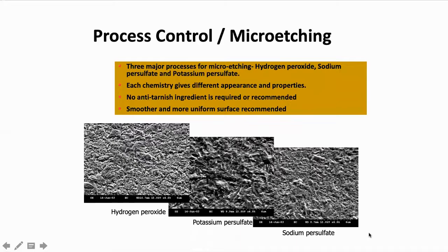So again, process control. I can't stress enough the importance of microetching. Not only must you have a clean surface, but you must have a properly microetched surface. With all three of these, hydrogen peroxide sulfuric acid, potassium persulfate, sodium persulfate, you must have a sufficient microetch that allows you to get at least 20 to 30 microinches of copper removal. With that said, these will give you a much better opportunity to have a uniform coating.